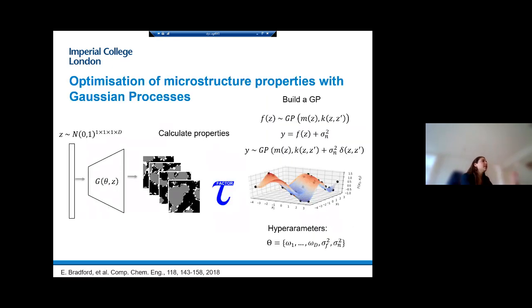So once we have obtained what we call our function that fully defines our microstructure, one interesting thing that we are aiming to do for the next steps, and I'm going to show you a glimpse of what we're doing at the moment, is to see if the z space that also defines the generator can be optimized in order to obtain different microstructural properties. The way we do that, by linking all these processes from the z space to the calculated property, is that we try to build a Gaussian process. A Gaussian process is a surrogate function that can approximate what's happening from the z space to the desired property to optimize. So this is what we're trying to implement now.